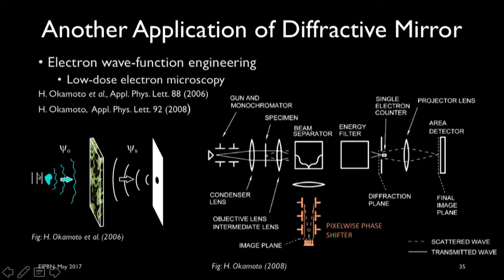You can imagine a plane wave of electrons coming in, interacting with a sample, with a phase object. That object will modify the wave function of the electron. So this psi o here is the modified wave function of the probe electron. And then if we have a diffractive element here, a transmission diffractive element that has a structure or pattern that is exactly the inverse Fourier transform of this modified wave function, then we can expect the beam that goes through to be focused on a spot on our detector. That's the psi s. So if by placing this transmission diffractive element we get to focus the electron, then we can be sure that we guessed the structure of the sample correctly. The structure of the diffractive element is exactly the inverse Fourier transform of the sample.